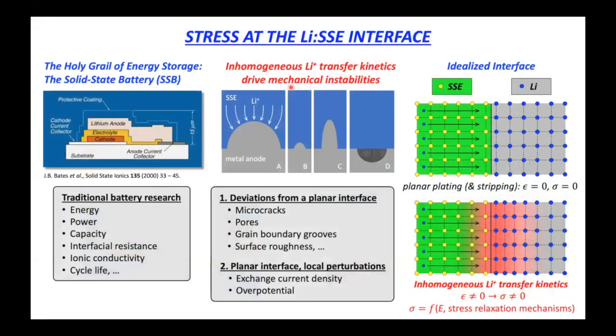Right, so as I'm sure many of you are aware, research in the field of solid state batteries has really begun to step out of this traditional electrochemistry box, I'll call it, and really started to think about how these non-uniform lithium ion transfer kinetics are driving these mechanical instabilities that form at the interface between the lithium anode here and our solid electrolyte separator. Right? So this schematic in the center of the slide does a pretty good job of graphically communicating the basic problem for us.